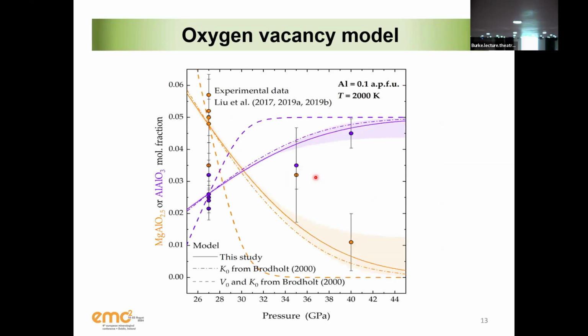So what we can do with all this data is, of course, forget about it, or we can say, okay, let's see if they make sense. And what Giacomo did was create a thermodynamic model which shows how the coupled substitution mechanism and the oxygen vacancy mechanism change as a function of pressure for a given aluminum content and a given temperature.